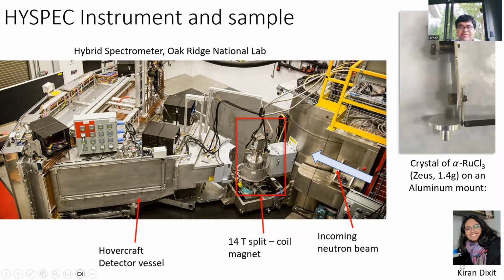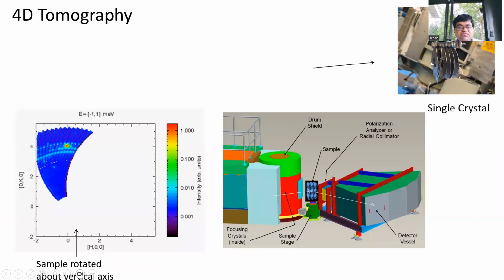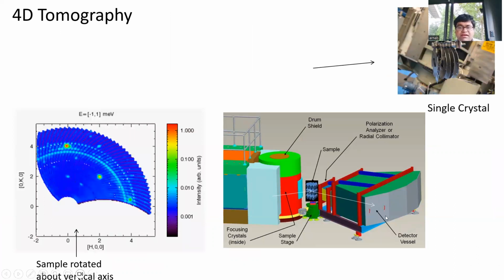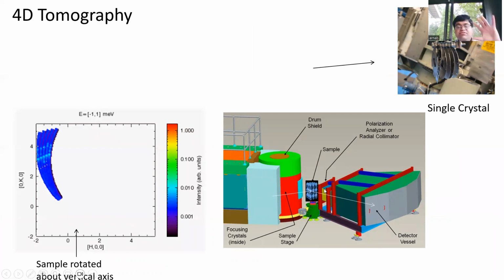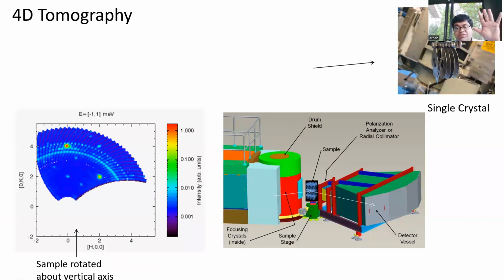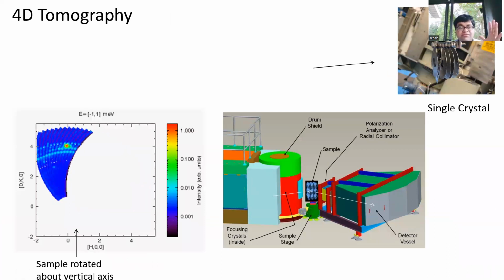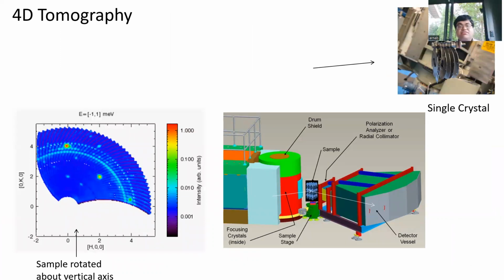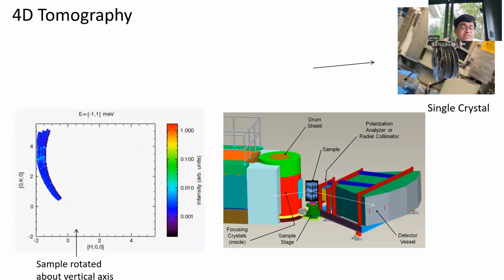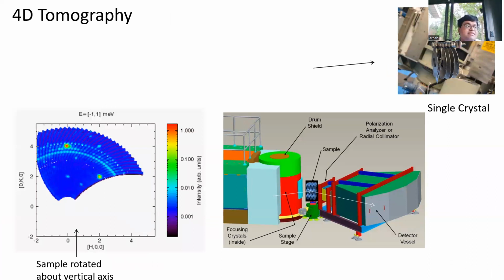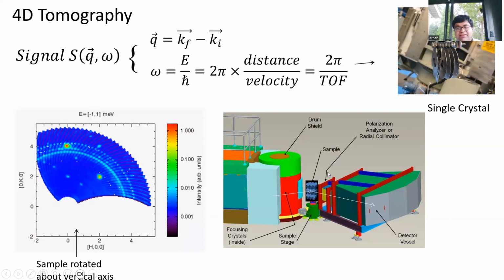This kind of goes right there. The sample is right there, and we have to fix the samples very carefully so that they don't move in a magnetic field. The way we do these experiments is using something called tomography, where we constantly rotate the samples, and we do a 4D reciprocal space tomography to capture the entire signal. The detectors are 2D, but we can get 3D signals that way. We stitch together all the 2D slices from every rotation.